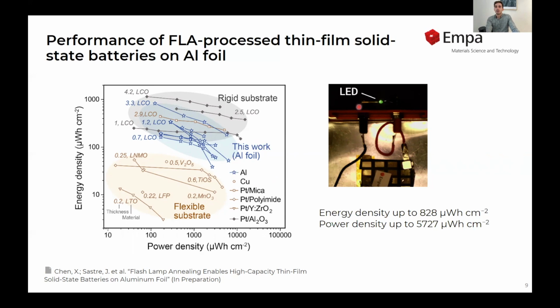And with our devices, we are even capable of powering an LED. This is a footprint of 0.15 square centimeters, and it's able to power a small LED. And here are the energy densities and power densities that we are able to achieve with this processing, rather comparable to what has been previously reported for rigid substrates.